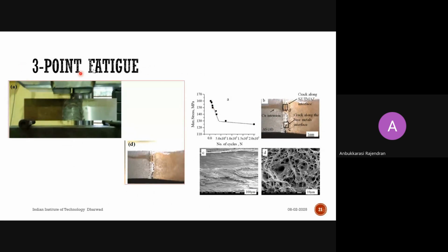So another test is the 3-point bend fatigue test. We wanted to see the background, like how the material behaved when we tested under tensile load. The fracture behavior was quite different. At the interface, here you can see the aluminum-copper interface, the failure happened. Then later we could see the propagation along the copper side. We expected it to propagate along the interface, but instead the propagation direction went into the copper side.